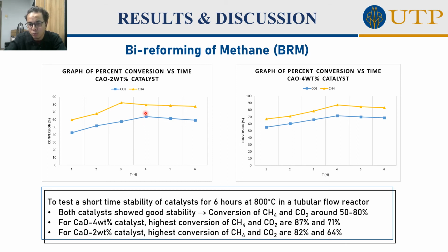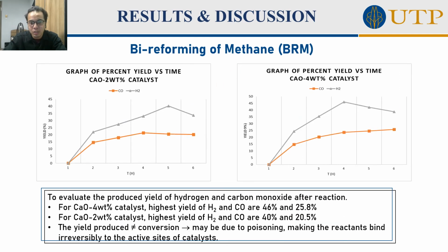So from here, we can conclude that the conversion of CaO 4% is higher compared to CaO 2%, which makes the loading of Ca significant in the catalyst to make the conversion higher compared to lower loading of Ca. And also from here, we can conclude that the conversion of the bioreforming of methane and also carbon dioxide is better compared to other catalysts. So next is bioreforming of methane in terms of yield.